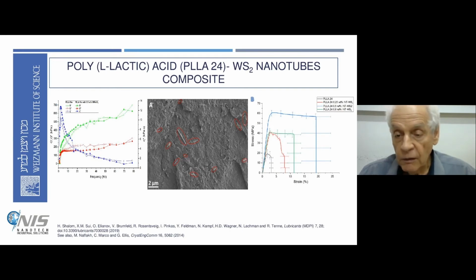You see the stress-strain curve. We take the nanotube-polymer composite, pull it from two sides, and measure the force we apply and how much it elongates before it breaks. It starts to show failure here, and eventually breaks at this point, so the force goes down dramatically. This is the typical strain-stress curve of the polymer.